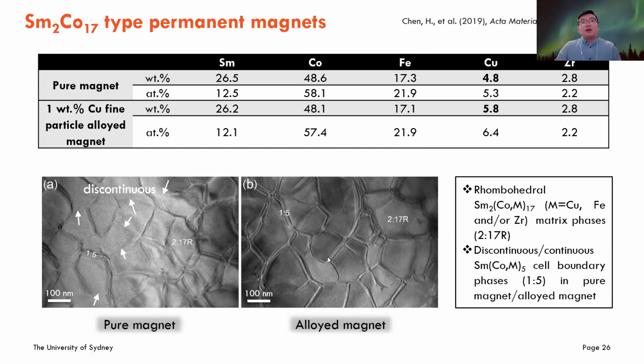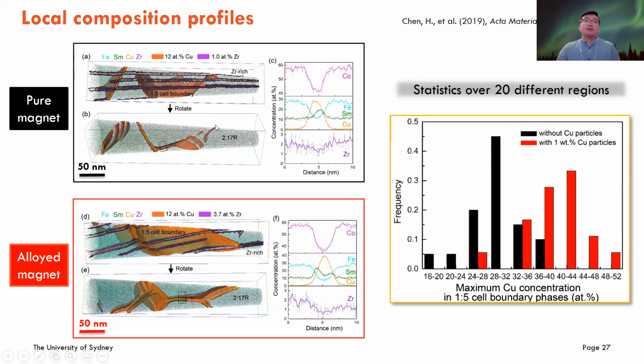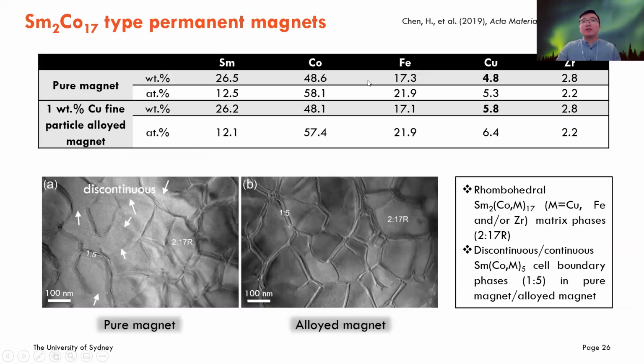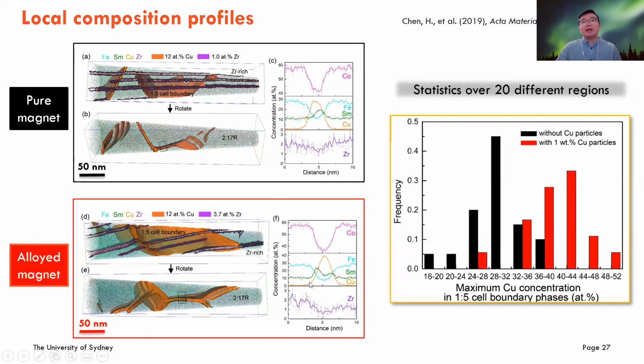What we do here is we add some more copper fine particles in the base magnet, because what we target is to increase the copper concentration in the 1:5 phase here. And again, by using atom probe tomography, we can identify the different concentrations of the constitutive phases in the pure magnet and also in the copper alloyed magnet. It should be mentioned that the previous pure magnet also has copper here, but we just add some more copper in the system, and we can directly see the copper enhanced a lot in the 1:5, the typical phase here. You can see the maximum ratio is around 40 atom percent compared with 30 atom percent for the pure magnet.